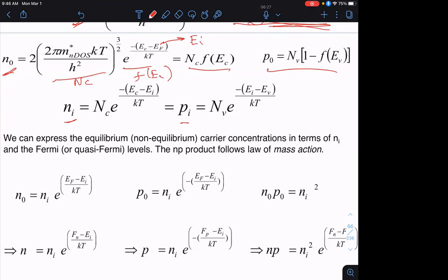These heat waves have an average energy of, say, kT, the thermal energy. And then a few of those photons might get absorbed and they can excite an electron from the valence to the conduction band, or equivalently, they can break some of these covalent bonds. In this process, of course, every time I create a conduction electron, you have to have a corresponding valence hole, right? So that's why Ni must equal Pi under intrinsic conditions, okay?